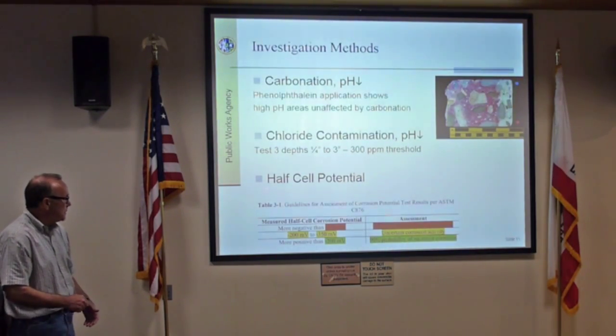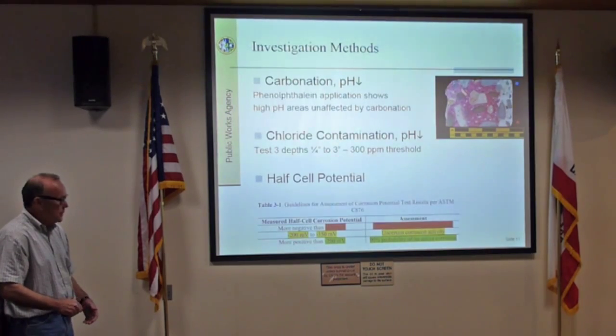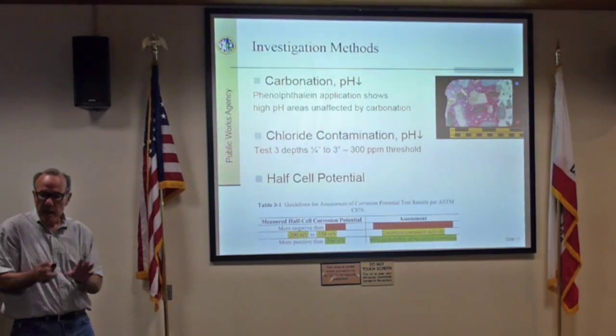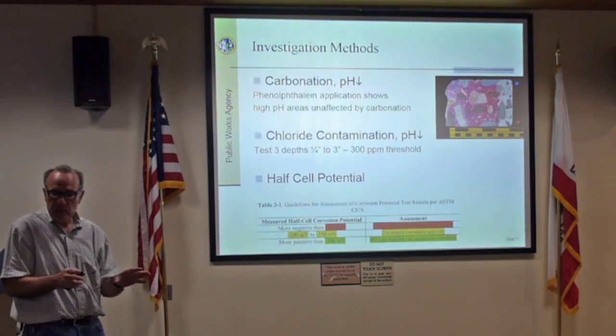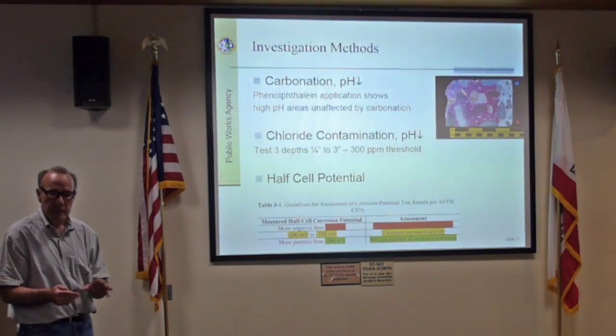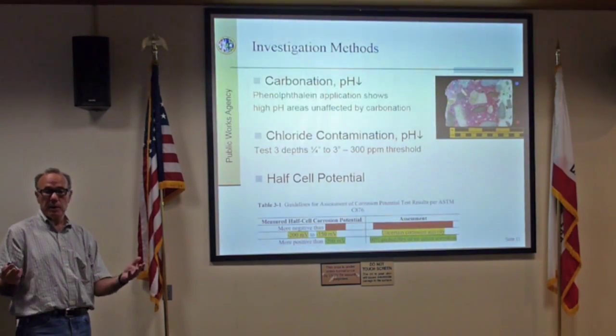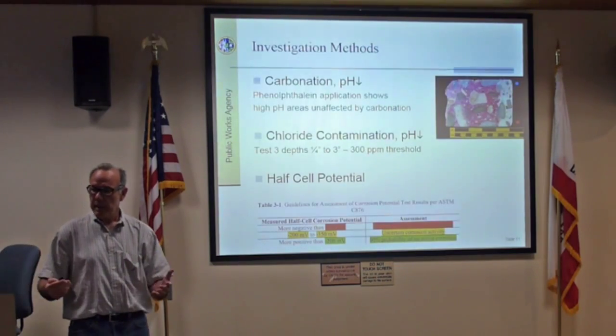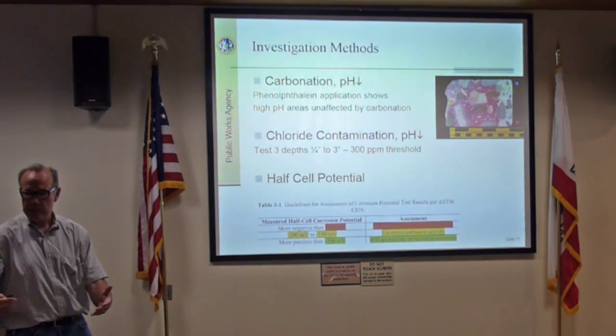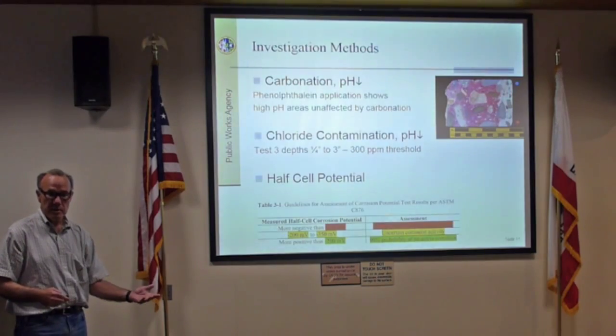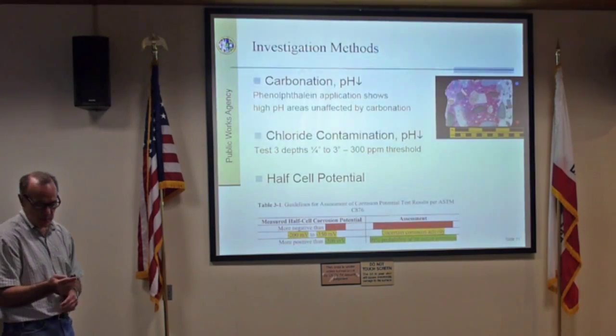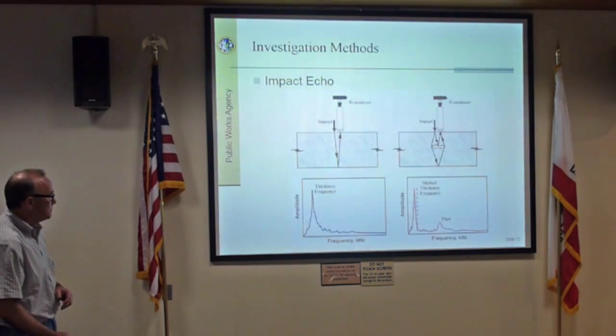And then the half-cell potential test is a method that tells us whether it's corroding or not corroding, based on threshold values, but we don't really know how fast it's going to corrode. And that's really what you want to know. We know steel wants to corrode and go back to its natural state, but is it going to take 1,000 years or is it going to take 5 years? That has to do with the rate of corrosion.